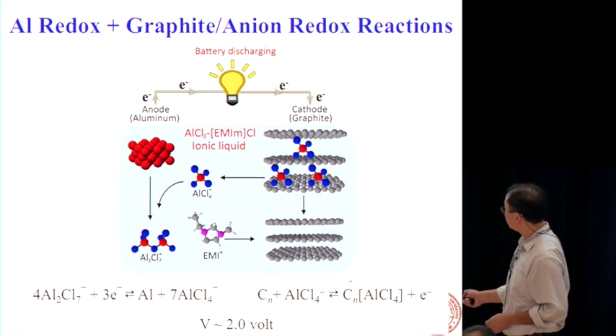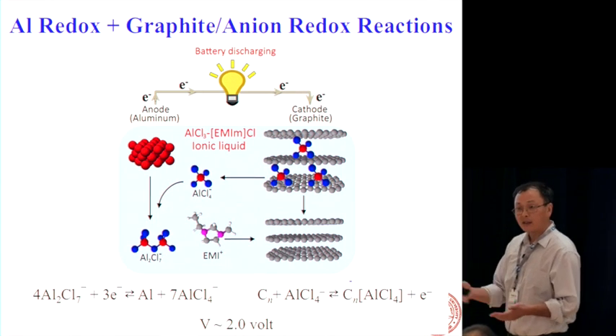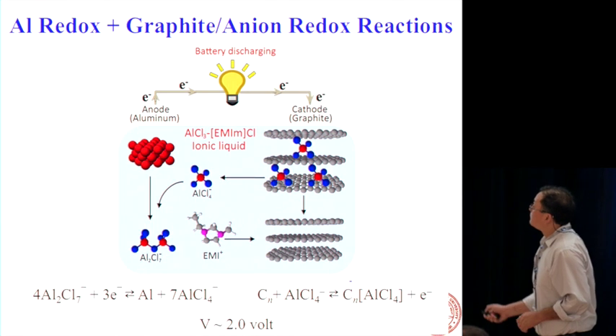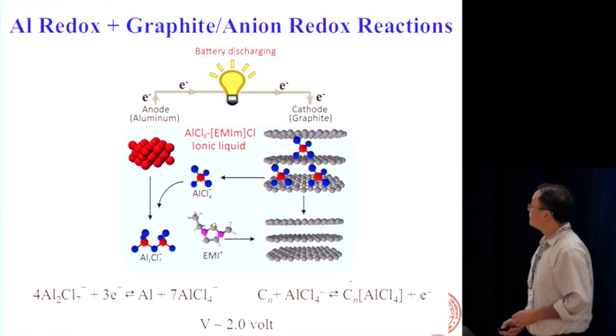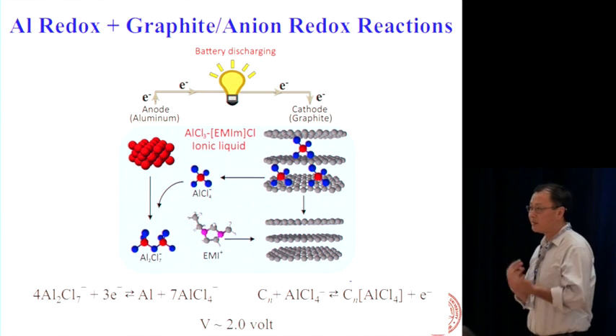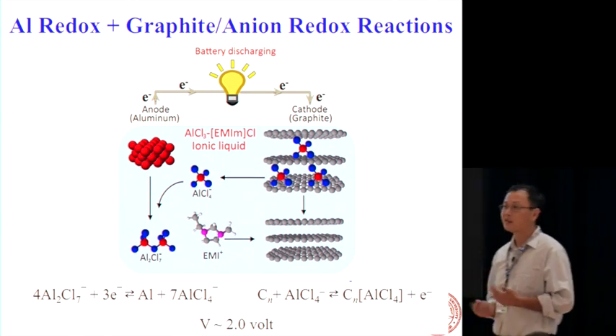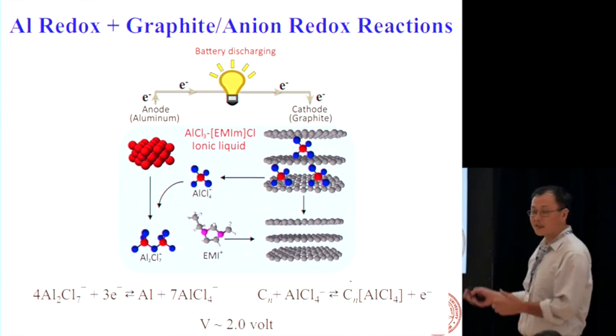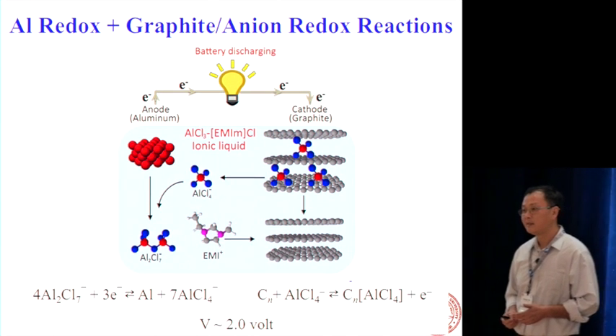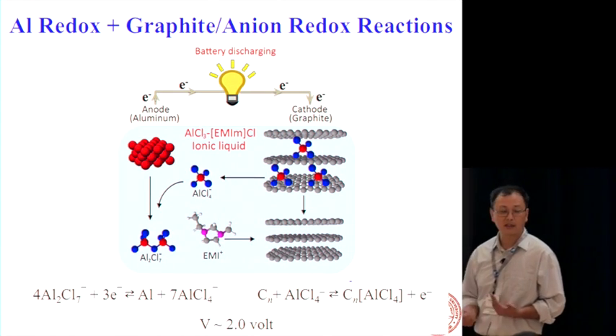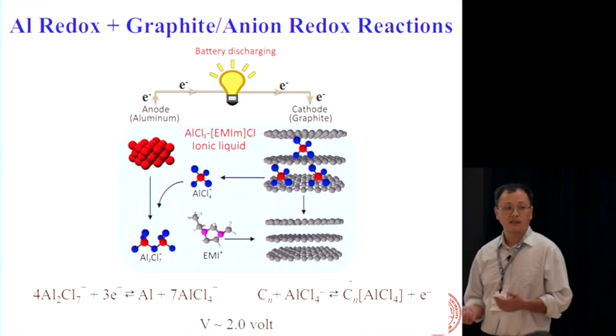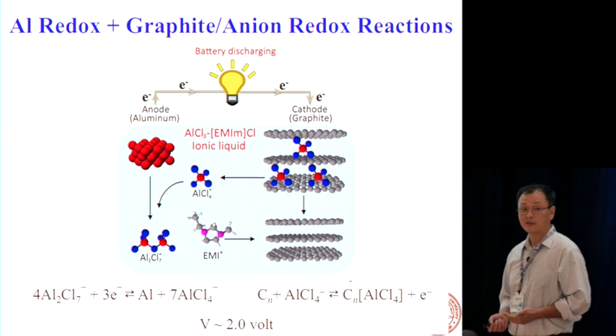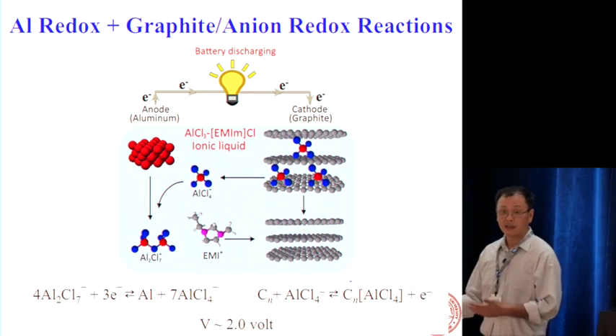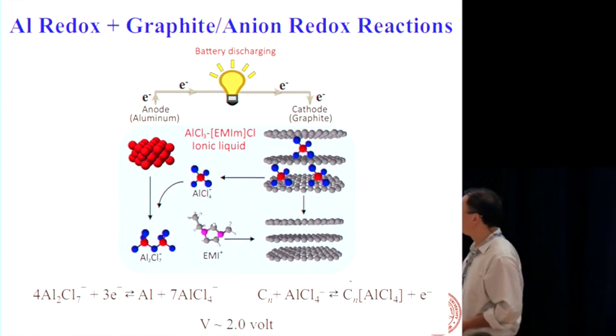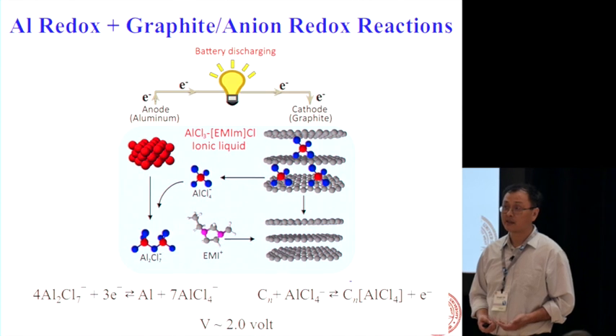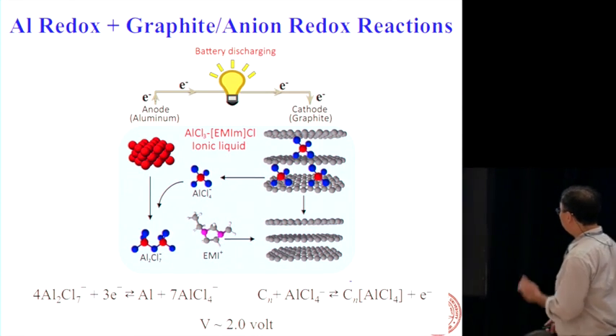It's actually these anions, okay, that's actually intercalating in between the graphite. And when this anion goes in, this side has to be neutral, so the carbon gets positively charged or gets oxidized. Okay? And when the anions come out, they get reduced. So it's a very classical redox reaction in electrochemistry, oxidation and reduction, and it's reversible. The intercalation here it's reversible. Actually, it's reversible for thousands and even 10,000s of cycles. Okay, we have data now on that.